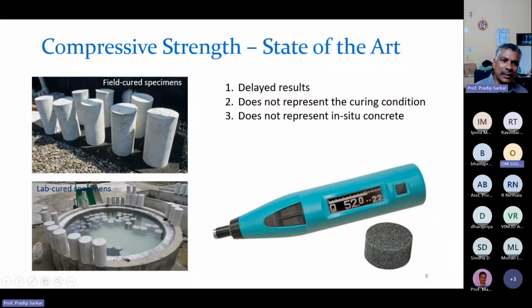And there is another instrument, the rebound hammer test, that is often used, and it only gives you the strength of the cover concrete. It does not tell the actual strength of the concrete that is inside the structure. Only the surface layer strength we get from the rebound hammer. Even the design code says that reliability is plus minus 25%. So we cannot trust the value of the rebound hammer unless we do core testing or many other tests in conjunction with this test.